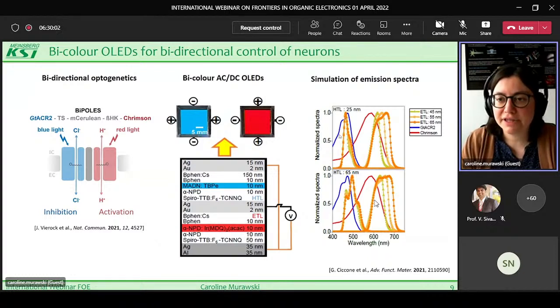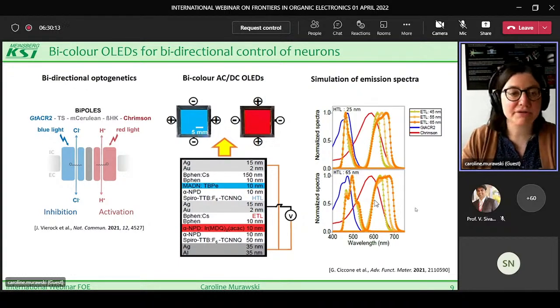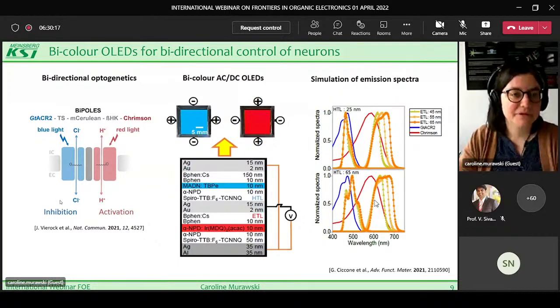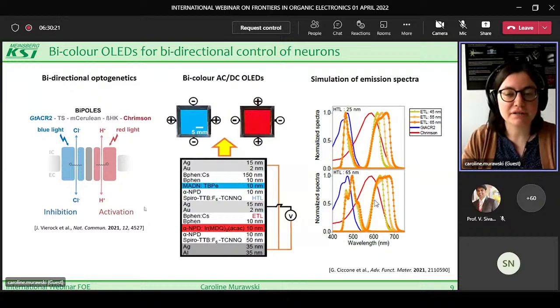So in our final device, we used a 25 nanometer hole transport layer for the blue and 65 nanometers, so this yellow curve here, in order to have a good spectral separation, so that we will not stimulate the blue channel by the red device or the red channel by the blue device.